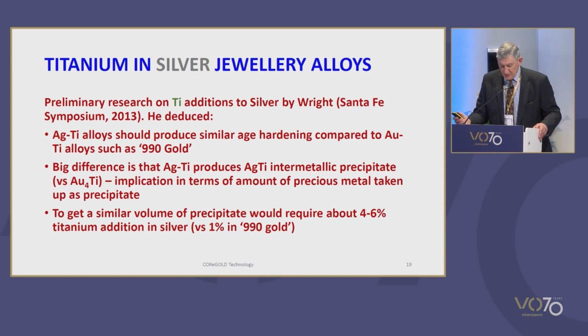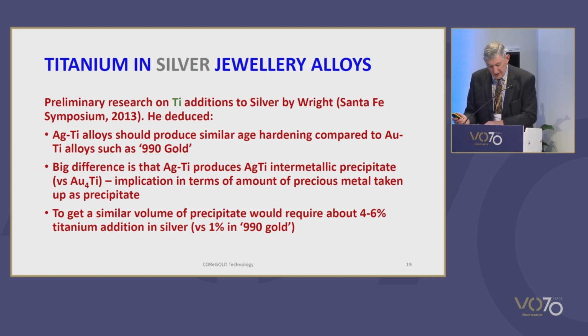A big difference is that the silver titanium system produces the intermetallic phase AgTi as the precipitate compared to Au4Ti for the gold system. This has implications for the volume of precious metal taken up as a precipitate. He also noted that the decrease in solubility of titanium on cooling to room temperature is much less in the silver system compared to the gold system. A further point was that the density difference between silver and titanium is about half that of gold and titanium. Thus, to get a similar volume of precipitate in silver would require about 4 to 6% titanium compared to the 1% we saw in the 990 gold alloy.